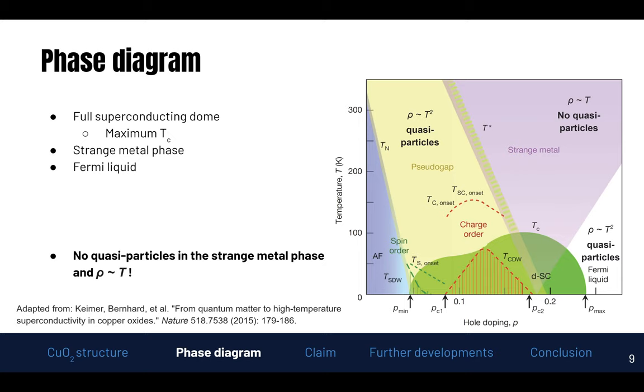If we look at the full phase diagram, there are some other things to point out. In both the pseudo-gap and the Fermi liquid phase, we find that we have a resistivity proportional to T-squared and we have quasiparticles in both regimes. However, in the strange metal phase we find a linear proportionality for as high a temperature as measured for the cuprate superconductors with hole doping, and we find no quasiparticles. This is weird because it means you go from a phase with no quasiparticles, cool down, and suddenly quasiparticles appear — and how all of this relates is simply not understood.